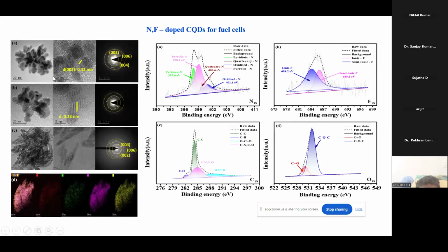So these are the TEM images. When we are doing N doping separately, the quasi-spherical part shows, which has nothing changes with it. It correlates with the CQD. And when we are doing F doping, the F doping shows the fringes. Usually the fringes will not form. Mostly metal particles get these fringes, but for fluorine halogen doping itself, we can get it.